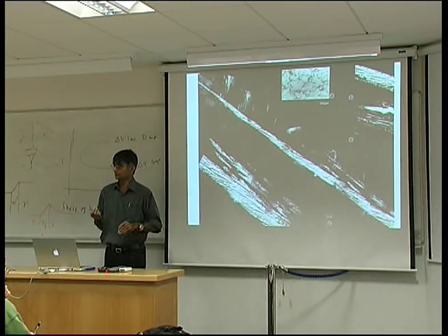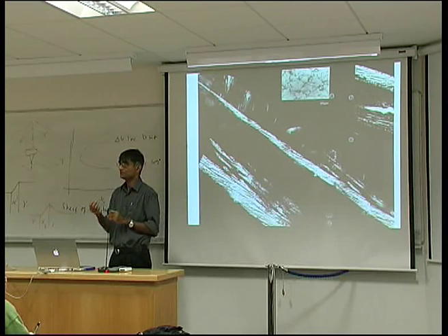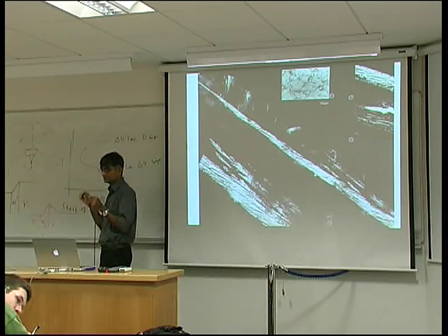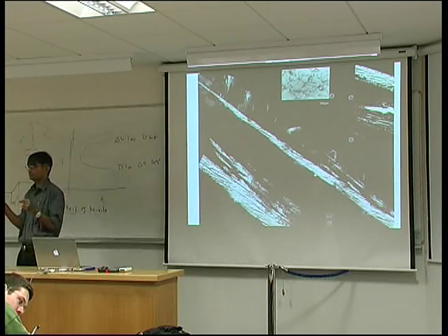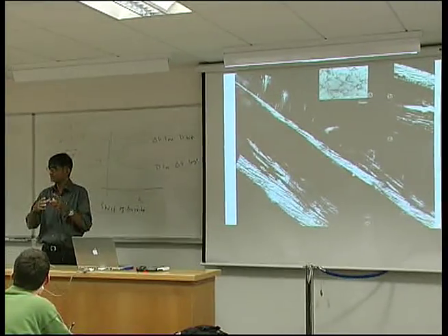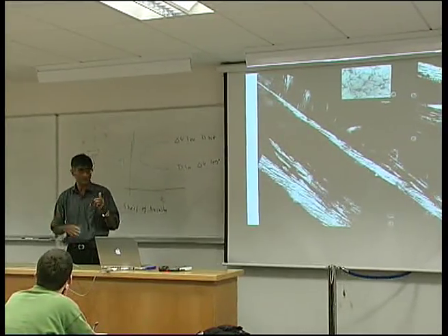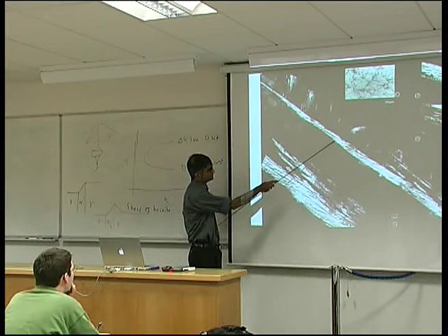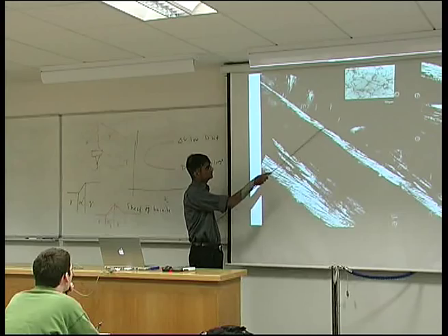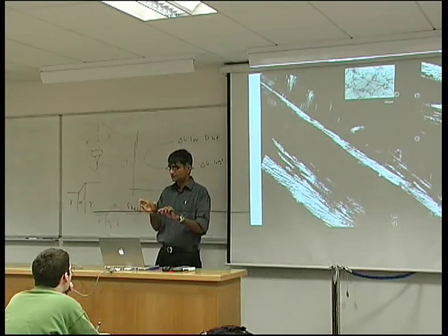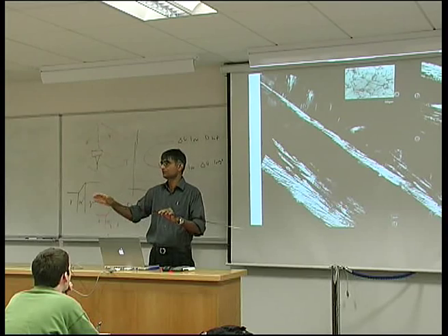Now this is very good for mechanical properties, because basically we have refined the scale of the microstructure enormously with this plastic accommodation killing the progress of the plate. And this is why bainite forms in clusters of platelets, or sheaves. You form a platelet, it stops growing, you have to nucleate a new one, new one, new one, and so on. So the transformation is progressing by a series of displacive transformations.